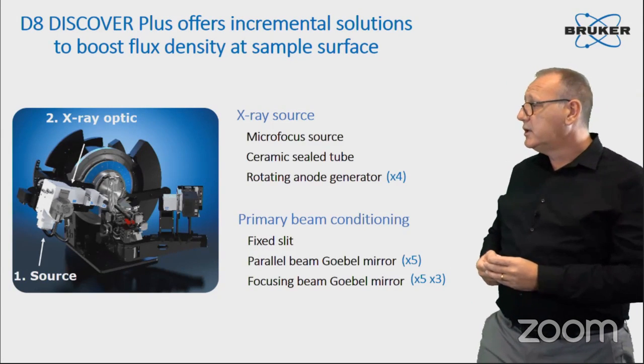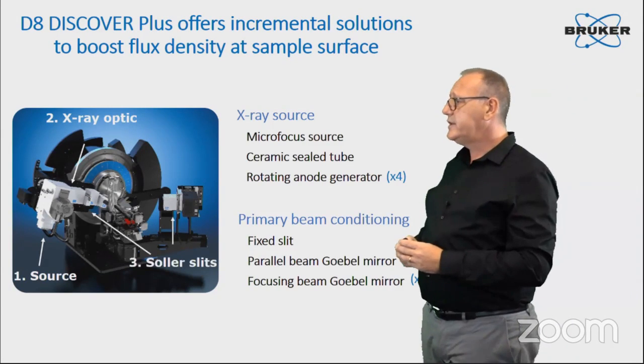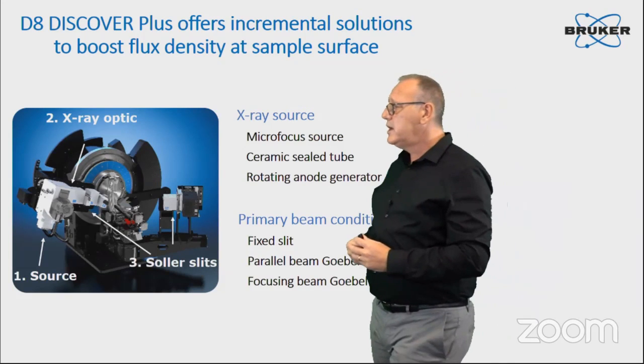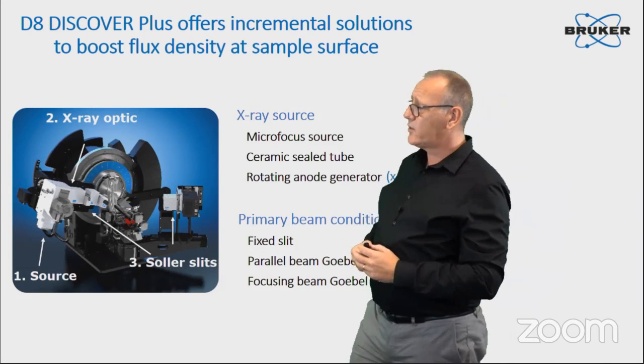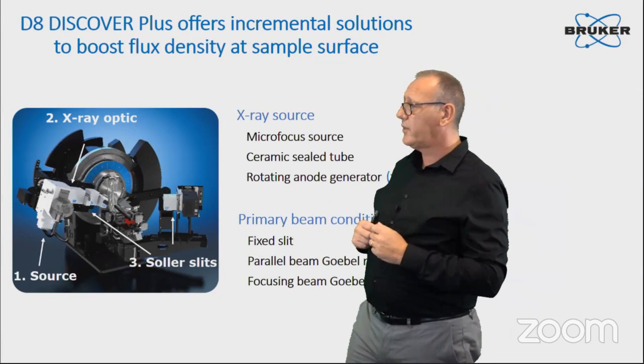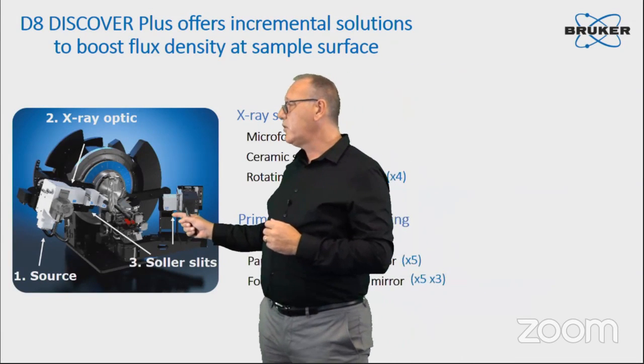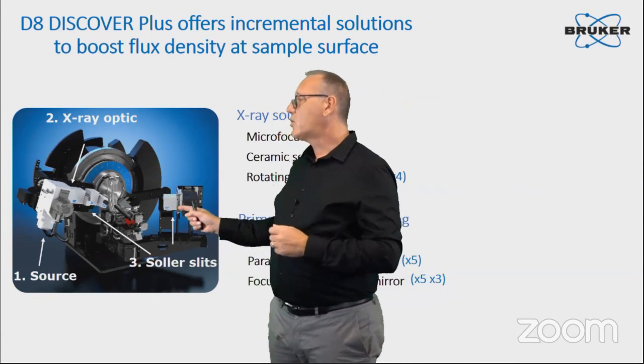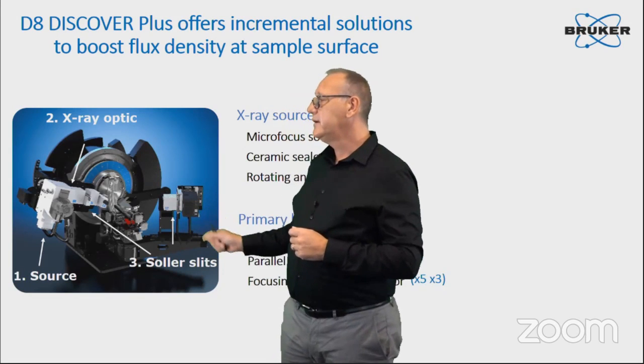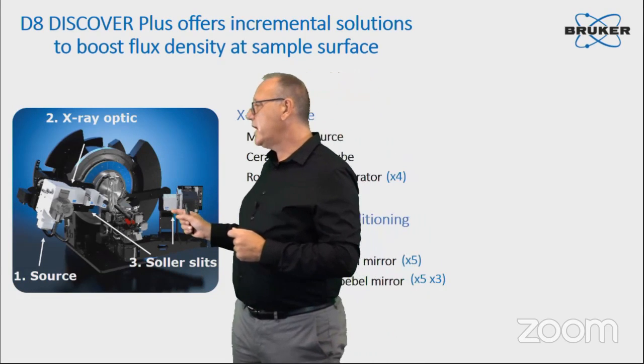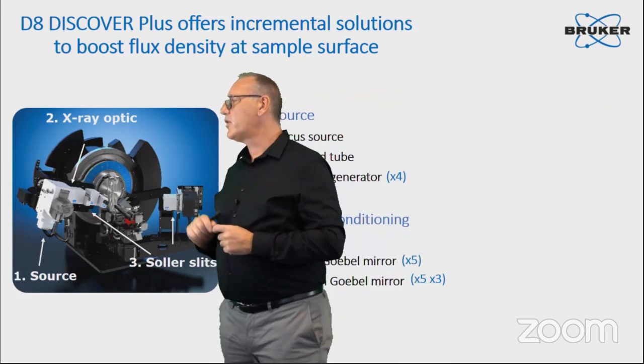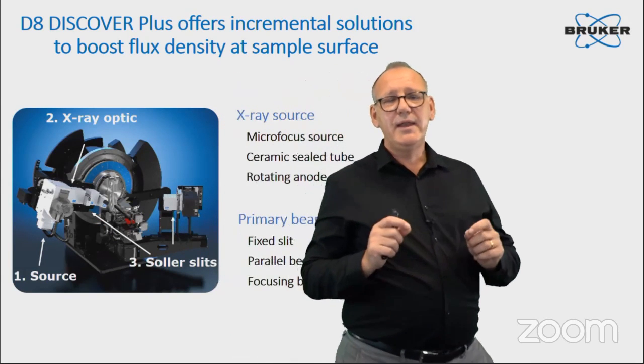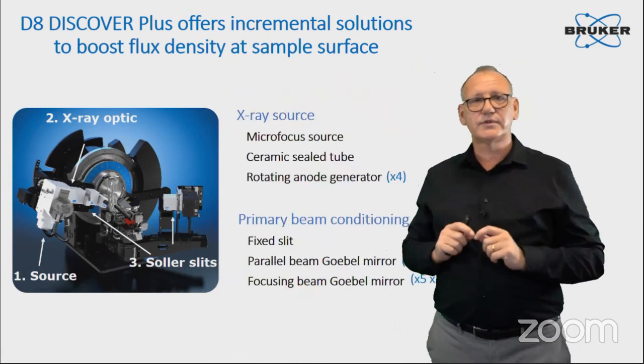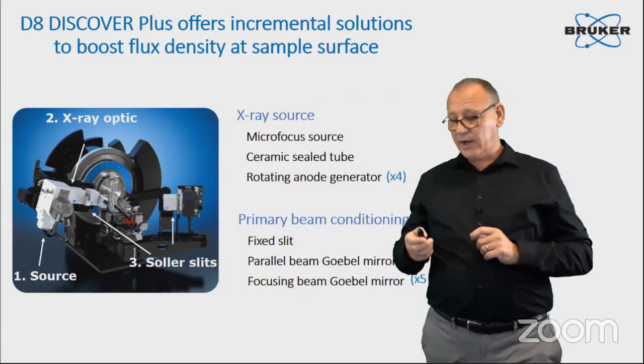The last component, and this is also a very important one, if you want to do grazing incidence diffraction, due to the large footprint on the sample, you need to use on the primary side here for coplanar GID a Soller slit, and for non-coplanar GID, one on the secondary and one on the primary side. And depending on the acceptance of those Soller slits, you may lose again quite a lot of intensity.